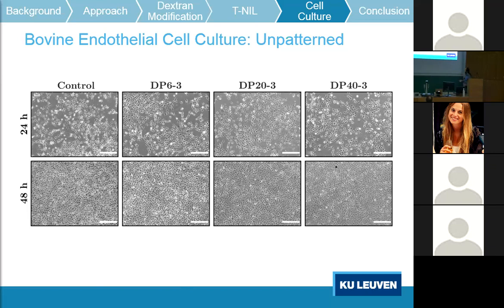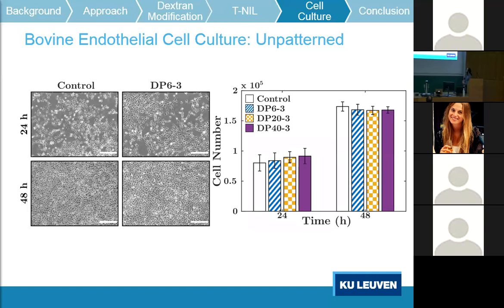And what I had observed was that the cells were able to attach quite effectively to my materials. They had the morphology that I had expected, and that they were able to grow and proliferate rather readily. And when comparing the situation between the control and the different materials, there was no observable difference in these preliminary assessments. So at this point, I thought, okay, the cells don't hate my material, so I can see how these different surface properties are able to influence, in combination with the topography, cell behavior. And that was quite interesting.